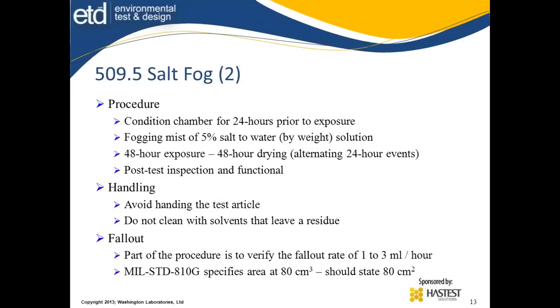Procedure typically calls for conditioning the chamber for 24 hours prior to exposure. If you've not run your chamber in a while, you've got to get it up to speed. The fogging or mist is a 5% salt water by weight solution, so 5% salt by weight to the equivalent water in weight. A 48-hour exposure with a 48-hour drying, alternating 24-hour events, is normal.